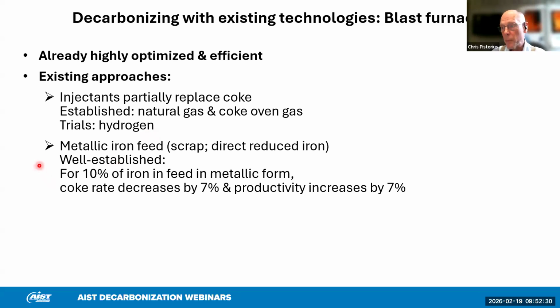Something that has much more scope, I think, is something that's done already, which is to change from feeding iron ore to partially feeding scrap or other sources of iron, reverts. And the numbers are, as you see, for every 10% of the iron that's in metallic form, the coke rate drops by 7%. And there is a productivity increase, which allows some companies to close smaller, arguably less efficient blast furnaces and use a bigger furnace with iron input to run at a higher productivity.